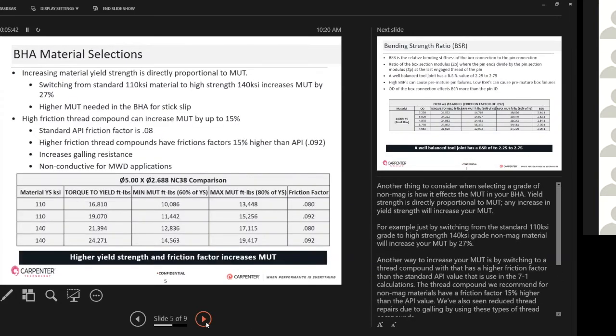So one other thing to consider when you're selecting the material for your non-mag is how it affects your makeup torque. Yield strength is directly proportional to makeup torque. So any increase in yield strength will increase your makeup torque. For example, just by switching from the standard 110 KSI grade to the high strength 140 KSI grade, you'll increase your makeup torque on the same connection by 27%.